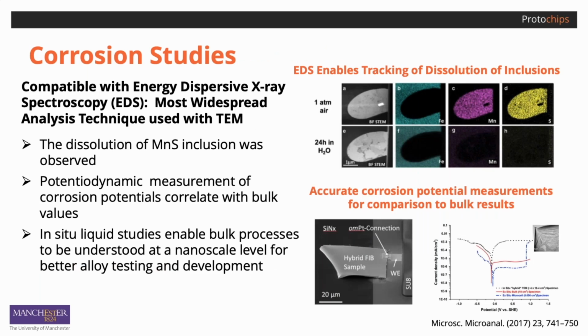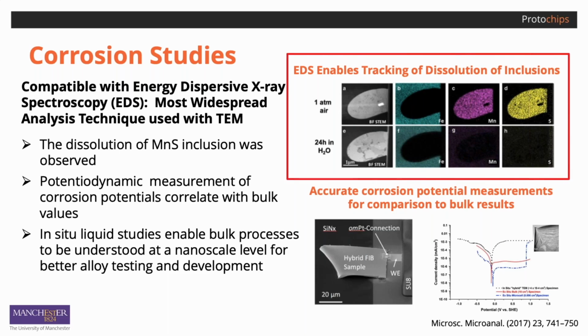Because Poseidon Select is fully compatible with energy dispersive X-ray detectors, elemental analysis can be performed in liquid. In this example, energy dispersive X-ray spectroscopy was used to follow the dissolution of a manganese sulfide inclusion in stainless steel. The inclusion is shown in the top row pre-experiment. You can clearly see the manganese indicated in pink and the sulfur indicated in yellow of the inclusion. The bottom row shows the same region after a 24-hour in situ experiment with exposure to water, and the inclusion is fully dissolved and no manganese sulfide remains.